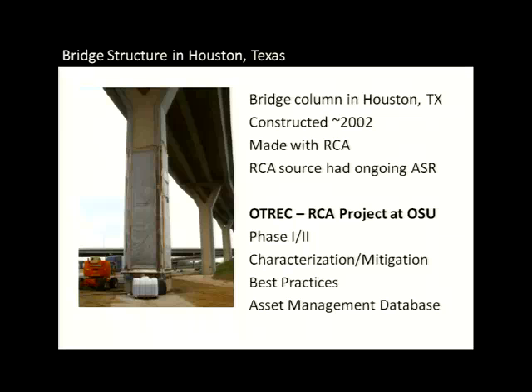So at the time, a very sustainable concrete mixture using concrete that's been taken out of service, so it's not going to be landfilled. It's put into a new structure. The problem was that the concrete that was used to construct these, the recycled concrete, was undergoing active ASR. When it got put into a new structure, it got put in with more cement that's supplying alkalis. It's an outdoor structure, and so it drives the reaction even further. And they had cracking beginning in these columns within about 3 to 5 years.